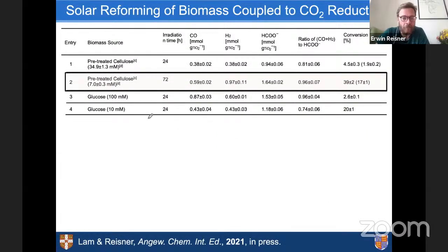So there was one interesting finding. This is the table, and I just would like to go to entry 2. So if we use this pretreated cellulose in this system, I've shown before that we form carbon monoxide, hydrogen, and formate. And it's interesting to see that we really form this very nicely in the 1-to-1 ratio if we look at CO and hydrogen, the products from the reduction, and the product from oxidation. And so an incredibly clean system, which we're happy to see.